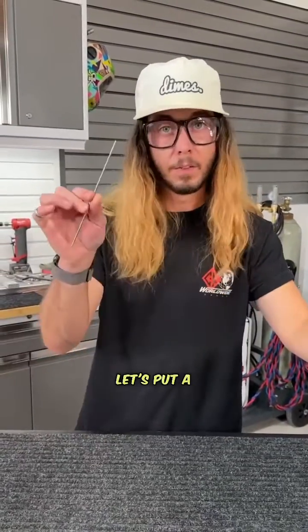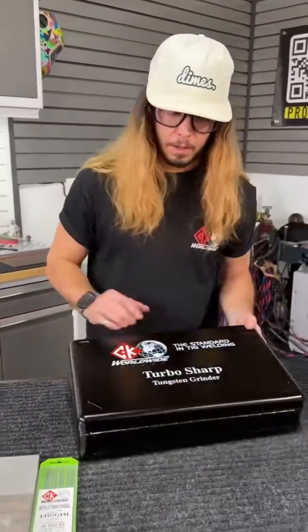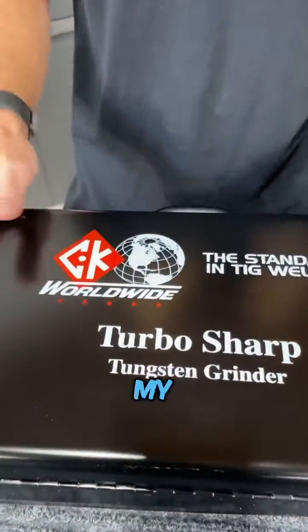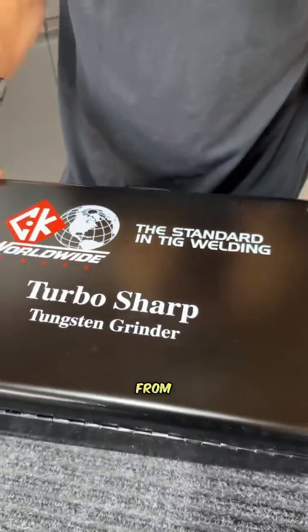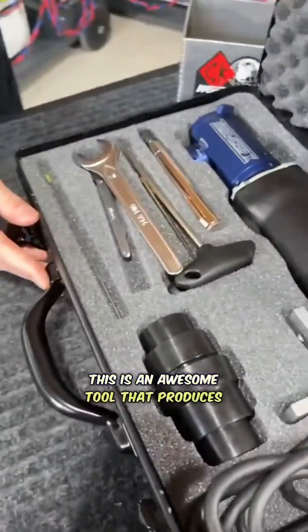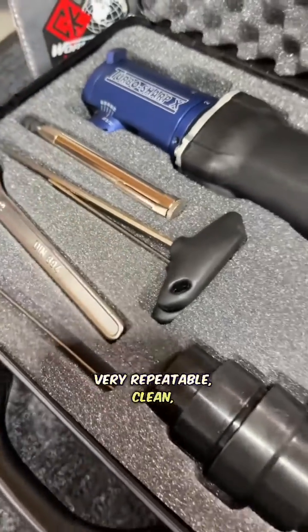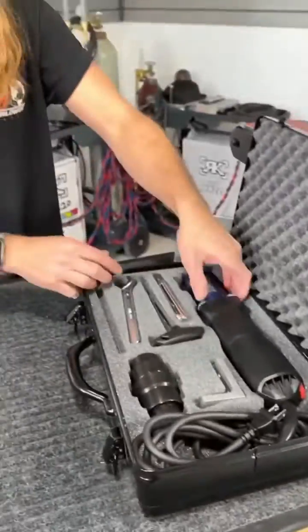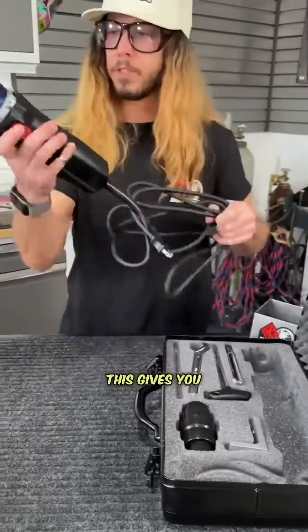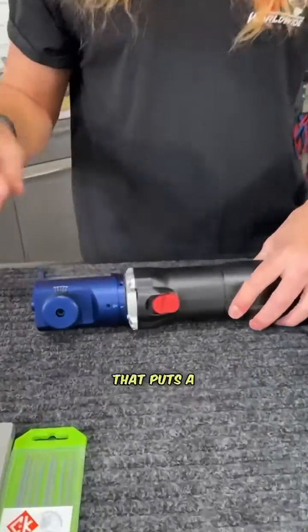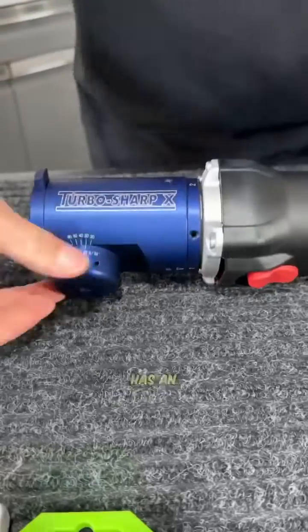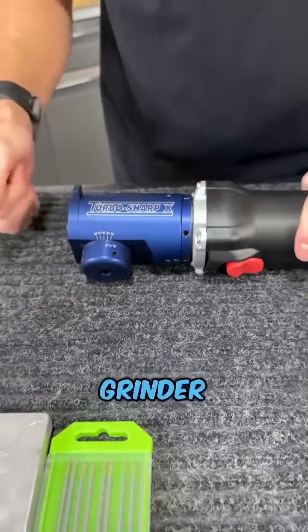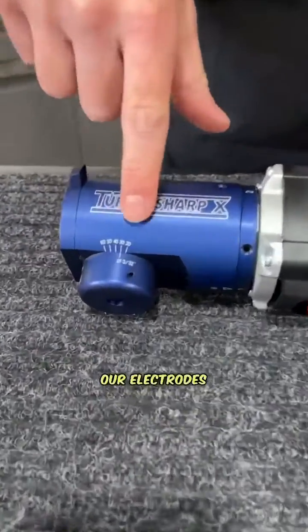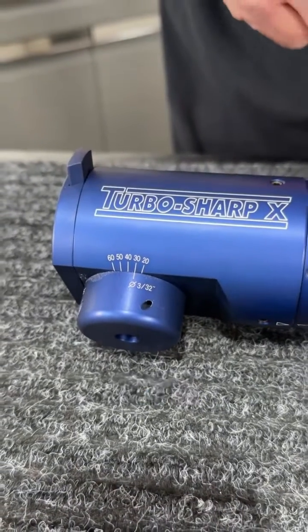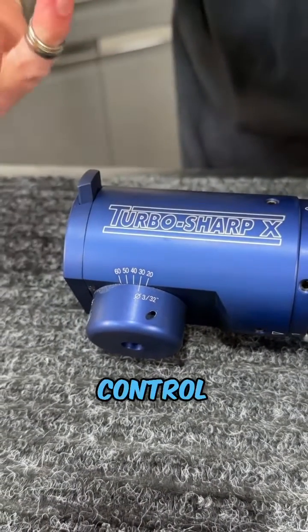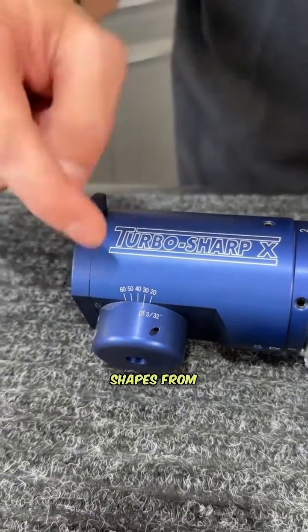So let's put a grind on this. The best way that I know how to take care of my electrodes is with the Turbo Sharp from CK. This is an awesome tool that produces very repeatable, clean, perfect tungsten grinds. This gives you a linear tungsten grind with a diamond grit that puts a very, very smooth finish. This grinder has an adjustable angle on the grinder head, so we can adjust our electrodes from 20 degrees all the way to 60 degrees, so we can get a large array and control of different penetration profiles and arc shapes from this.